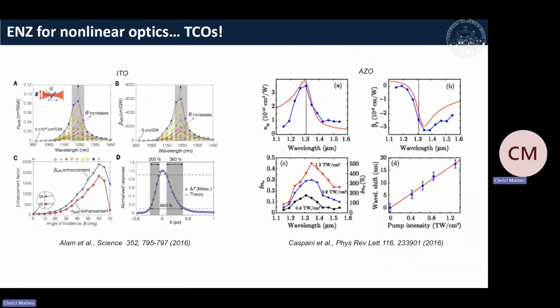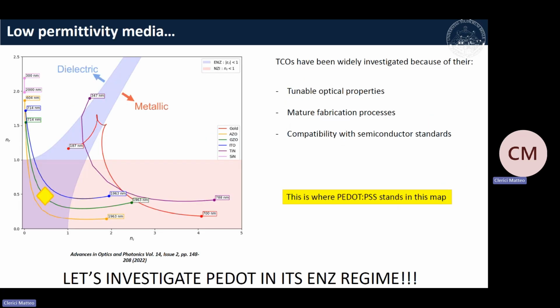Now, one of the things that happened over the years was that TCOs were appointed as the elected materials for these nonlinear applications, because TCOs have a very mature technology, and you have a certain degree of flexibility in tuning their properties when you fabricate them. So somehow you can choose where you place your ENZ condition according to your fabrication step. Now, when we looked at PEDOT:PSS and noticed that it also had an ENZ crossing in the infrared range, we asked ourselves, how does it compare with TCOs?